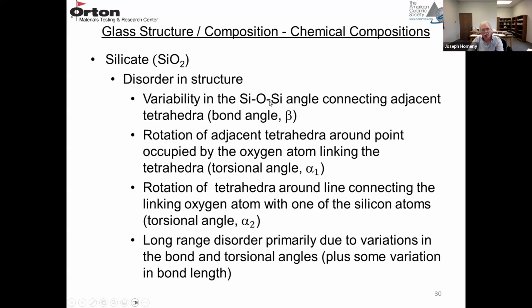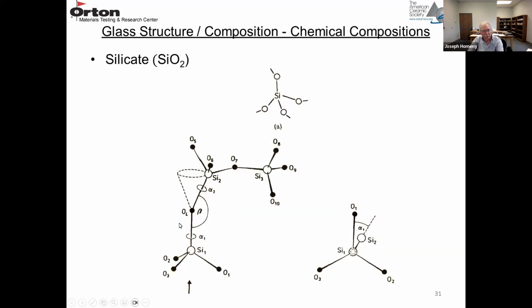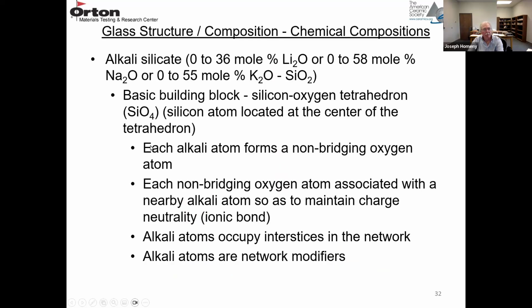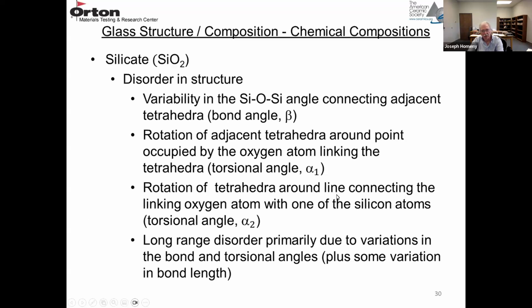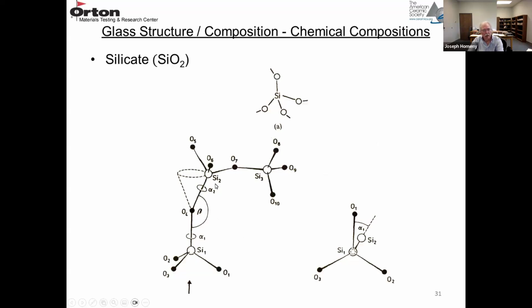So variability in the Si-O-Si angle, that's beta. Rotation of adjacent tetrahedra around the point occupied by the oxygen atom linking the tetrahedra. This is a torsional angle alpha 1. That's over here. So this tetrahedron can rotate to form a disordered structure. Then the rotation of the tetrahedra around the line connecting the linking oxygen atom with one of the silicon atoms. This is another torsional angle, alpha 2. So this is alpha 2, indicating this cone-shaped rotation. So bond angles and rotation of the tetrahedra create a disordered structure. And again, this is your basic unit, Si, with 4 oxygens.